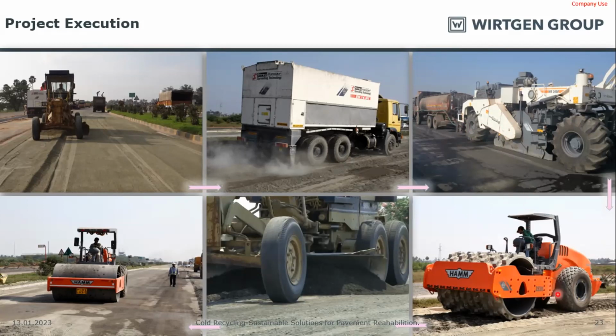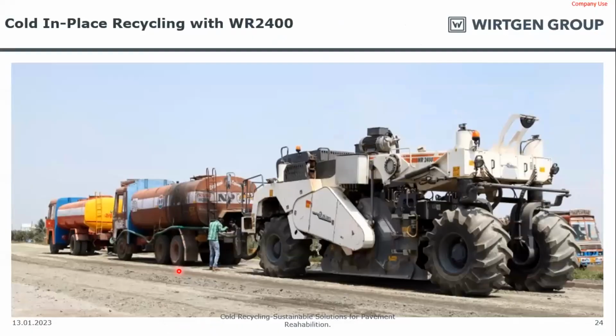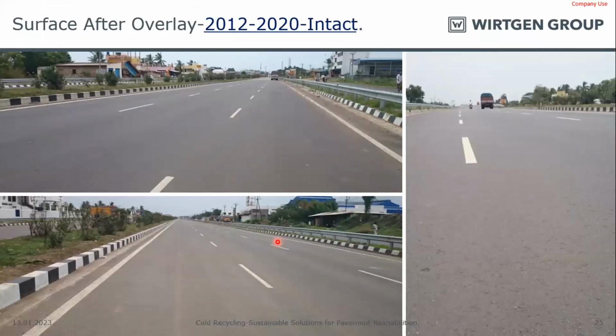After this process, we bring in the roller. It's a 20-ton roller to get better compaction results. And then we grade it to get the profile. Then we have the single drum roller and the pneumatic tire roller to follow. So this is the procedure of how we execute it. Some more pictures: you can see the bitumen tanker and a water tanker coupled to the machine. So this was the asphalt layer. It was intact till 2020 and we just needed some minor rehabilitation to follow after this process. So this road was completely intact.